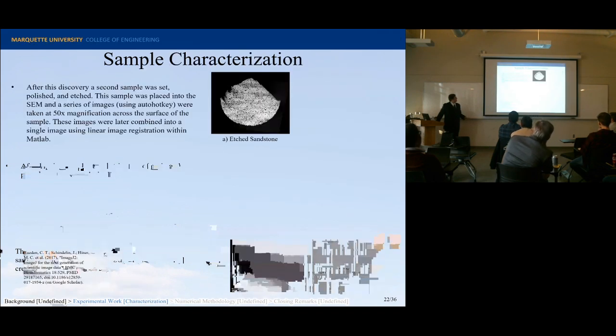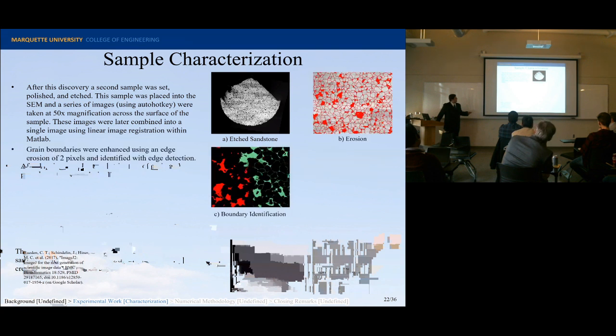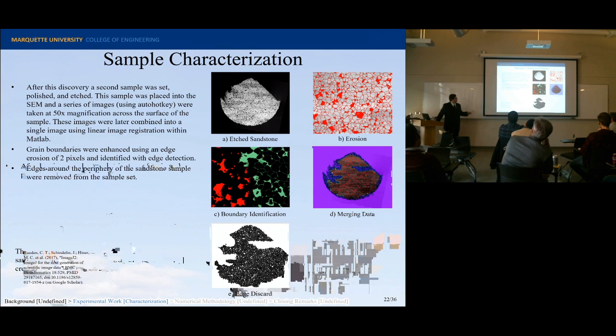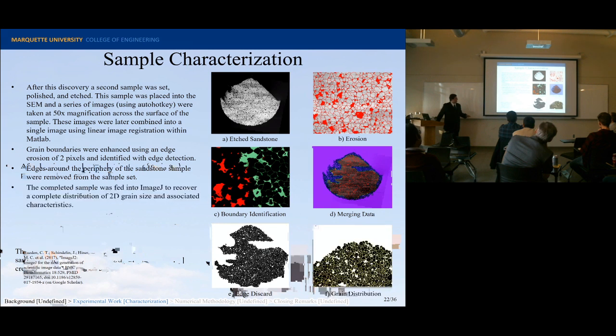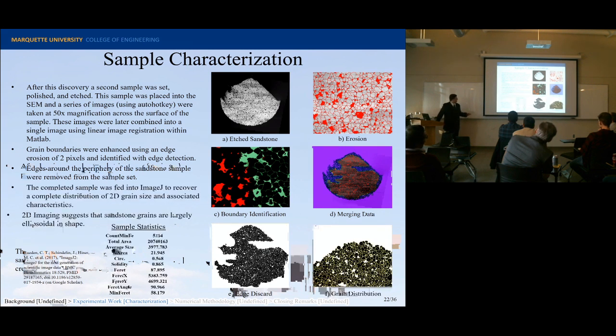Once I have my etched sandstone, I put it through a linear image registration with MATLAB, combined all my pictures together, did some erosion, boundary identification, merged the data together, did an edge discard, and then found my grain size distribution. I could use ImageJ, and then I got some sample statistics out for all of my grains. I think I had a total count of 5,214 grains after I did the discard. That was to make sure that I didn't have any boundary grains or ones that were too small.